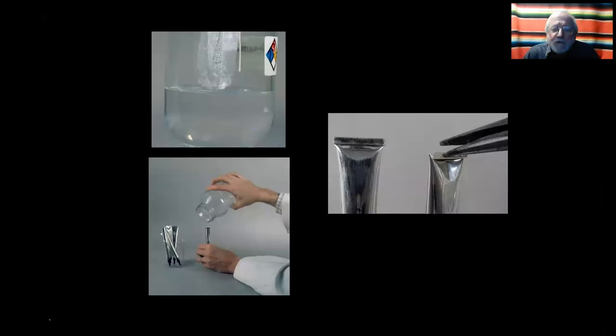And a lot of people ask, what is that percentage? That percentage works out to about 50% weight to volume. I've always made it up weight to weight just because it's easier to remember 50 grams than anything else. It used to be 50 and 100 and I would evaporate off some of the acetone. So this really works, but it's most important that you put it into tubes.